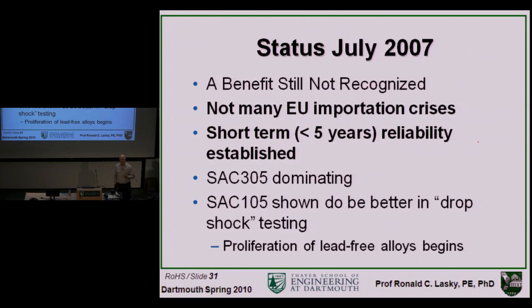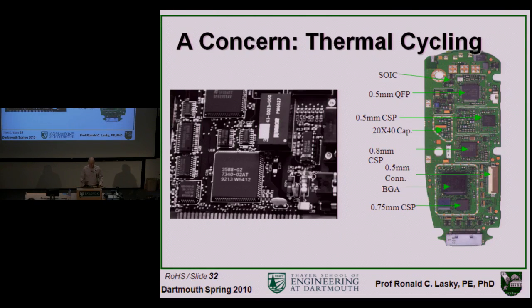And the fact that historically the type of testing that was done to show that electronics are good was thermal testing. In other words, if this is a circuit board and I turn this on and it's in a computer, and I think we all know how hot our laptops get, when you turn it on, the thermal coefficient of expansion of these different materials is not the same. And so you'll get stretching and shrinking comparatively, and you'll put stresses on these solder joints. And eventually the turning on and off can cause a crack in a solder joint. And so the type of testing that's done is called thermal cycling.